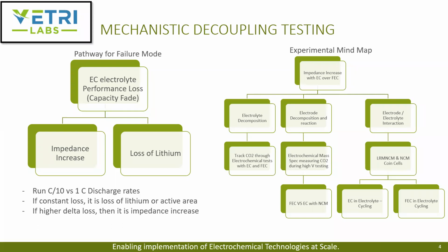There are three main buckets in terms of experimental approach to deconvolute this. One is they consider electrolyte decomposition as a primary mechanism, because in the past several papers suggested that mechanism, wherein the electrolyte containing ethylene carbonate actually decomposes faster at potentials approaching 4.5 to 4.6 volts when charging. They also considered electrode decomposition, including the electrode itself decomposing and the reaction and interaction between the electrode and the electrolyte.